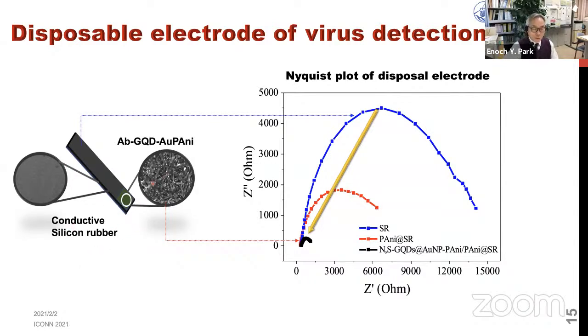And also polyaniline and the gold nanoparticle embedded polyaniline, this nanocomplex synthesized as mentioned before, was cast on the surface of this silicone rubber. Here, bare silicone rubber has a very high impedance value. However, when we coat polyaniline, it is almost half of the impedance value. And we cast GQD also here, very low impedance value. Therefore, we can use this kind of electrode for virus detection.